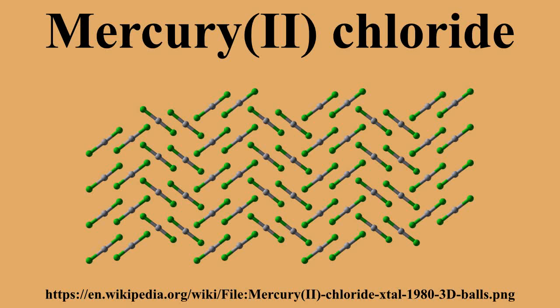Production and basic properties. Mercuric chloride exists not as a salt composed of discrete ions, but rather is composed of linear triatomic molecules, hence its tendency to sublime. In the crystal, each mercury atom is bonded to two close chloride ligands with an Hg-Cl distance of 2.38 Å. Six more chlorides are more distant at 3.38 Å.